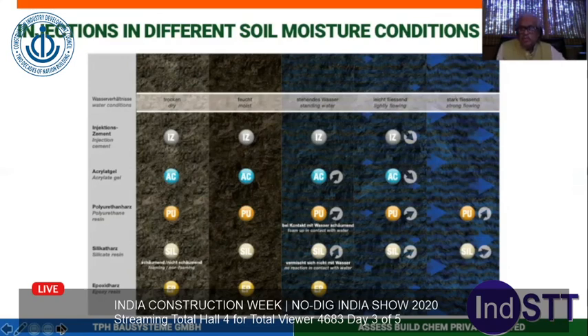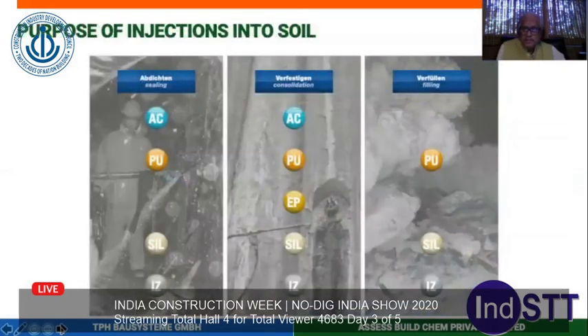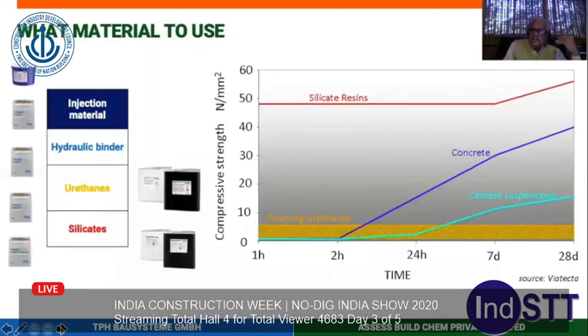Which material can be used when water is there, which material is to be used when there is no water, which can set in water, which can set without water, which can set in water or outside water. This is for the purpose of injection in soil. The reason I'm telling is, these are the strengths developed. If you see cement suspensions, micro cement, it develops very, very little after 24 hours. The strength developed is not even 10 newtons. After 28 days, because you are putting so much water into the cement suspension, it's only 15.